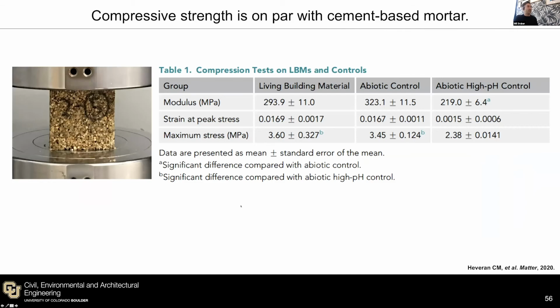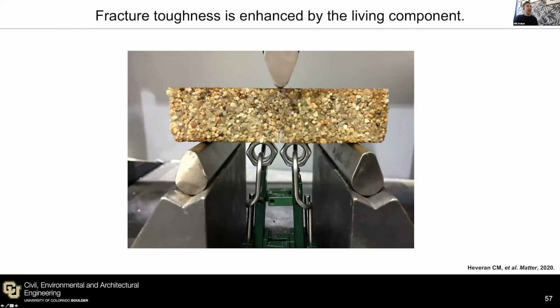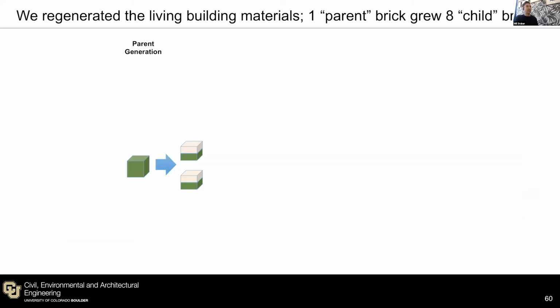This is for my civil engineers in the audience. The number I'll point out is the strength of the living building material, which is about 4 megapascals. If you're comparing the compressive strength, it's on par with a cement-based mortar, so the mortar that kind of surrounds the bricks in everybody's house. So not ultra high strength concretes, but also not trivial in terms of the compressive strength we're able to achieve. I'm going to fast forward here.